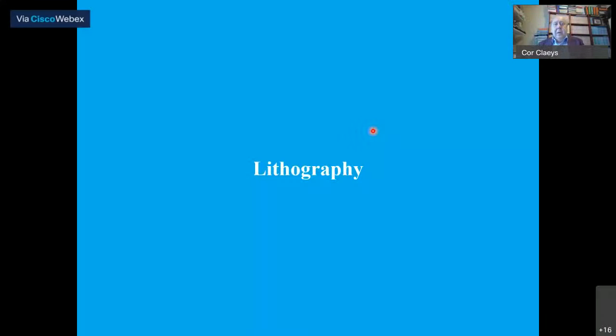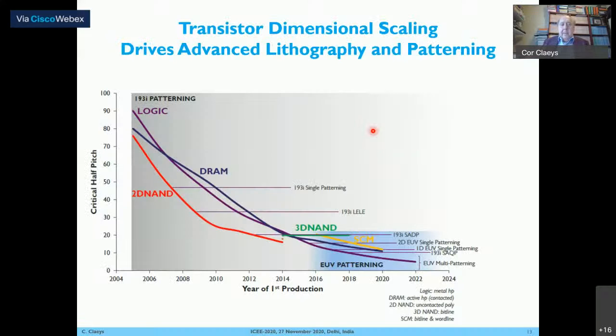Now, we cannot do scaling without thinking about lithography. And depending on the time and the type of technology you're using, we have been applying for a long time 193 nanometer lithography. And we have then extended that by going over to immersion lithography. And then we have been using double patterning. And we have been using litho-etching. We even went over to quadruple patterning. However, if you enter the area below 10 nanometer and you want to do cost-effective lithography, the only way to do that is by going over to extreme UV patterning.